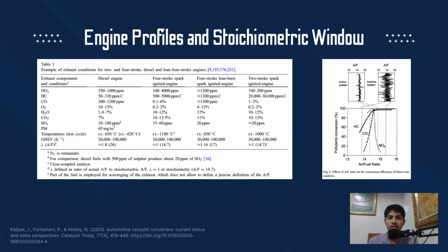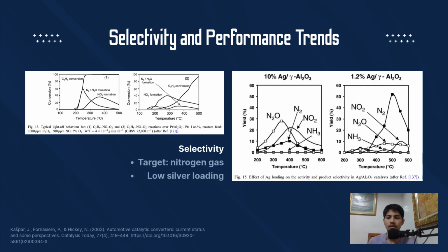However, high concentrations of hydrocarbons can actually inhibit nitrogen oxide reduction, essentially crowding the catalyst surface and slowing the cleaning process. We also investigated how fuel type and catalyst loading dictate selectivity, ensuring we produce harmless nitrogen gas rather than greenhouse gases like nitrous oxide.